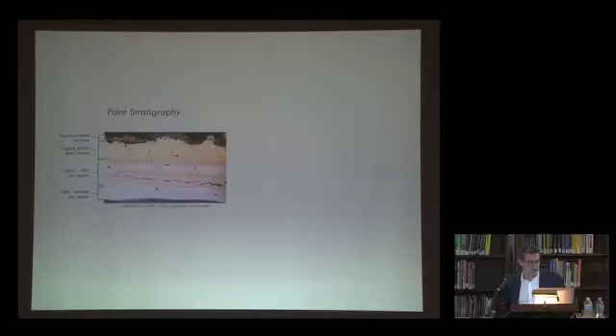Representative coating samples were taken, mounted, and viewed under magnification. The stratigraphy of these was, for all intents and purposes, the same. So this is a typical paint stratigraphy. I think we took 100 samples. I don't think any of them were different. Certainly the original coating wasn't different. There might have been other coatings that were applied over time. But here, I think this is a gunite sample, so here's a gunite surface.